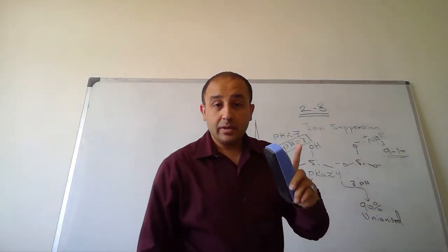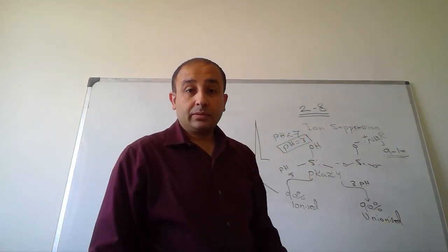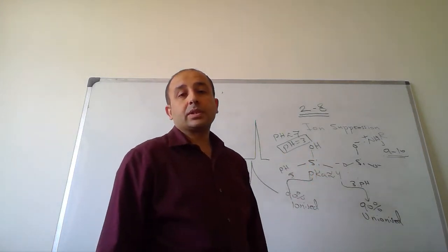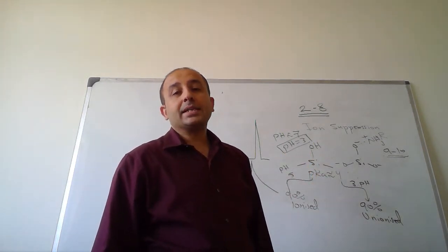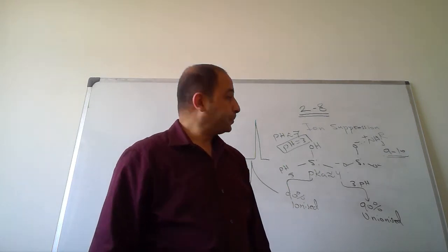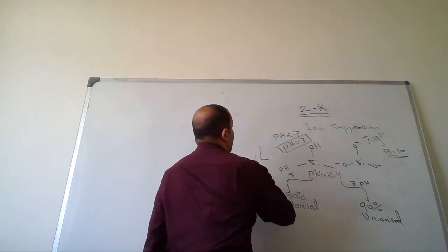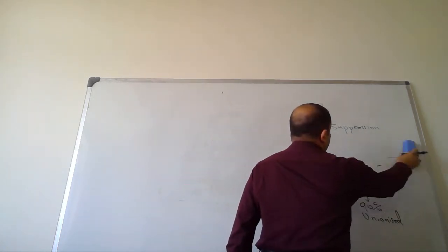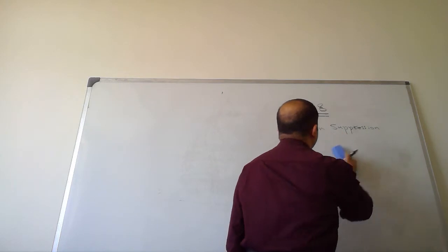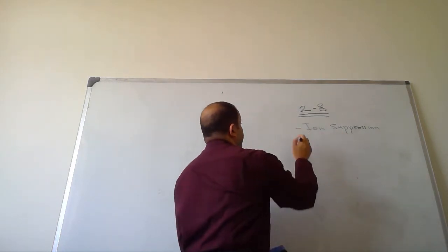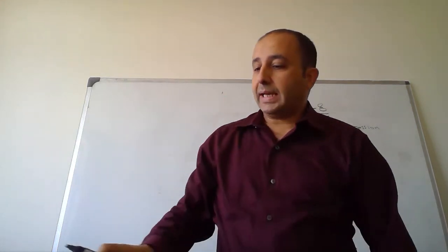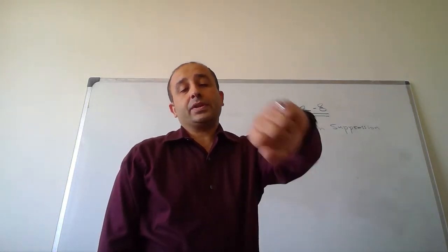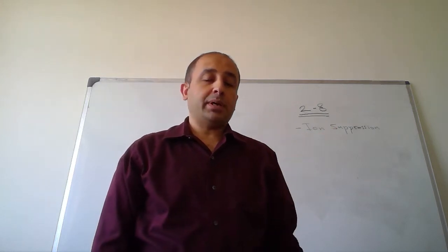So the only option for me is to suppress ionization of silanols by using an acidic pH medium. This is the idea of ion suppression, by which we can reduce the tailing effect of reverse phase columns, particularly with basic compounds.